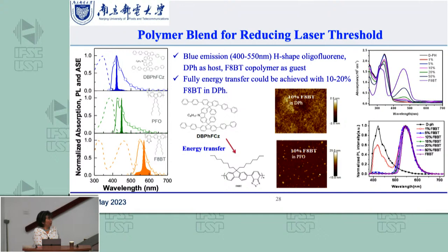And the emission part, this DPH, is this blue emission material. So that is the original DPH. With 1%, you can still see the emission from this material. But after 5%, the emission from this host totally disappeared. That means the energy transfer happened. All the energy from DPH, the host material, goes to the guest material. So by this way, it's possible to reduce the laser threshold as well.